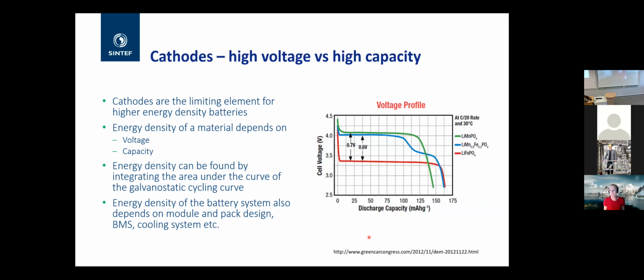So if we have a look at the cathodes, I'm going to start with that. Cathodes are currently the limiting element for higher energy density batteries. There's a limitation to how much lithium you can store in a cathode material and then cycle back in and out of the material. And you have two important factors. You have the voltage, which is indicated by, if you look at this figure here, where the plateau is. But then there's also the discharge capacity, or the specific capacity. That's often referred to in milliampere hours per gram.